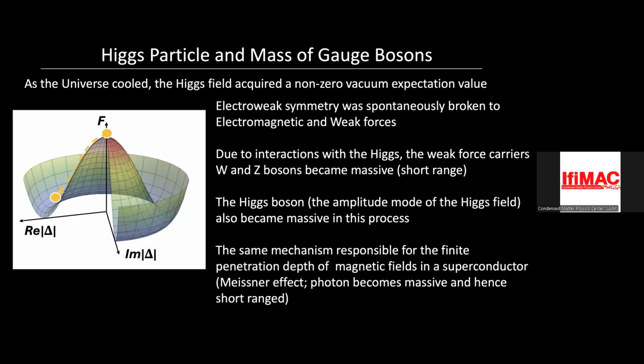So the interaction between the Higgs boson and the other bosons made both of them short-ranged. Okay. And basically, the same mechanism is responsible for the finite penetration depth of magnetic fields in a superconductor. Because in a superconductor, you have a condensate. So remember, this is what you do. You have something to condense. For example, the Higgs condensed. In a superconductor, you have the condensate of the Cooper pairs. So you need a condensate. The Cooper pairs, that field acquires a non-zero expectation value. And then when you have a photon, which is what a magnetic field is, going into your superconductor, the interaction between the photon and this condensate makes both of these things short range, which means really that the magnetic field cannot penetrate into your superconductor. So that's the mechanism.